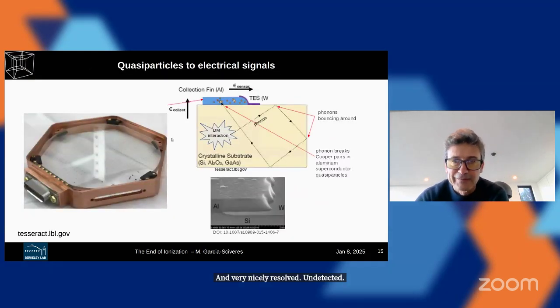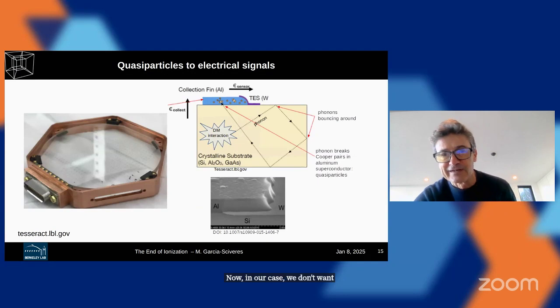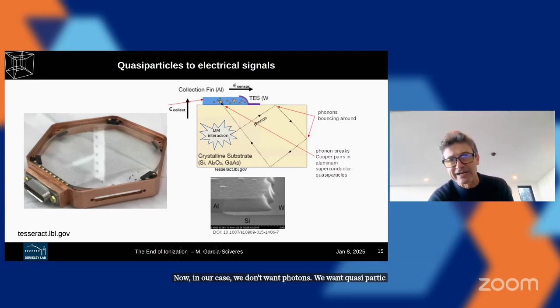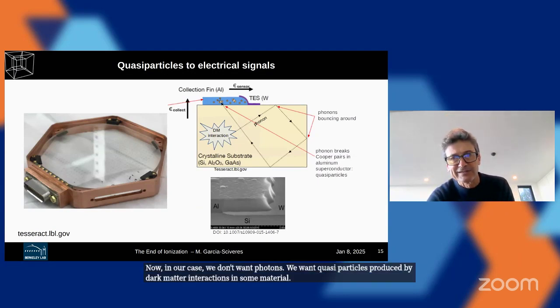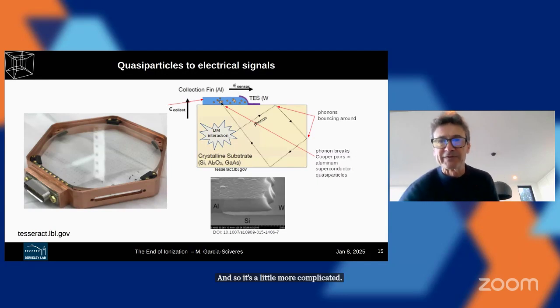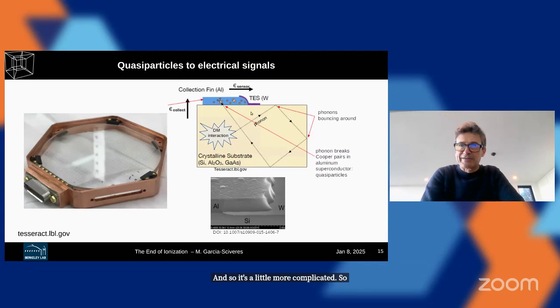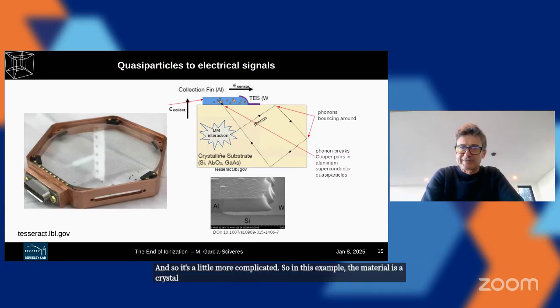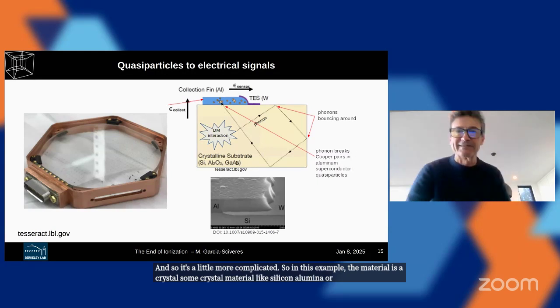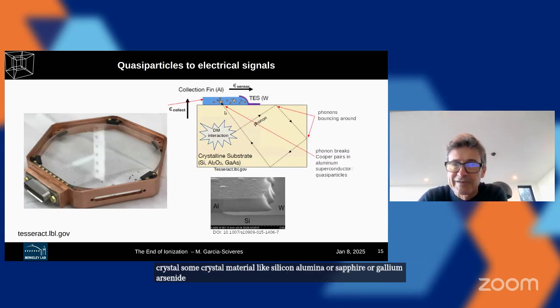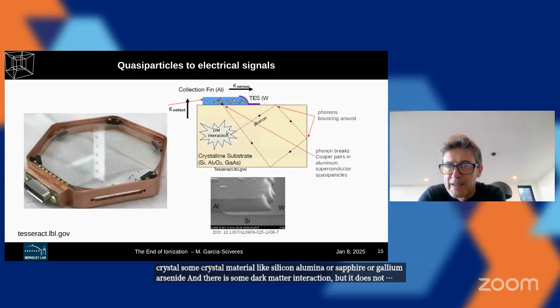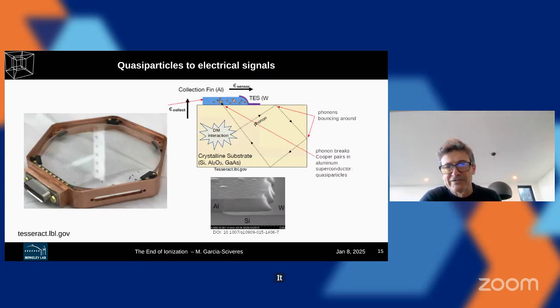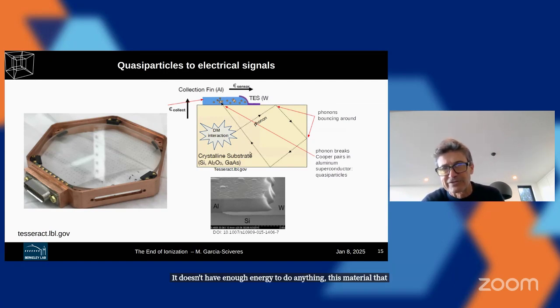Now, in our case, we don't want photons. We want quasi-particles produced by dark matter interactions in some material, and so it's a little more complicated. In this example, the material is a crystal, some crystalline material like silicon, alumina, sapphire or gallium arsenide. And there's some dark matter interaction, but it does not ionize. It doesn't have enough energy to do anything in this material that produces a free electric charge.